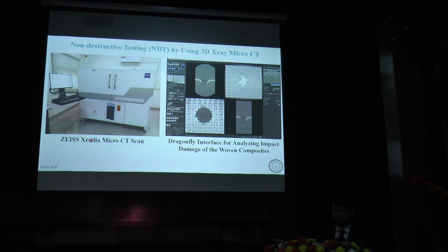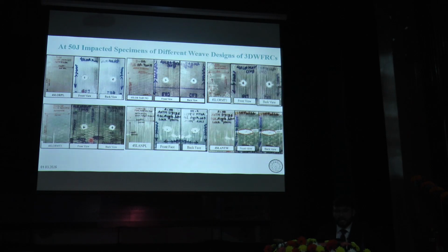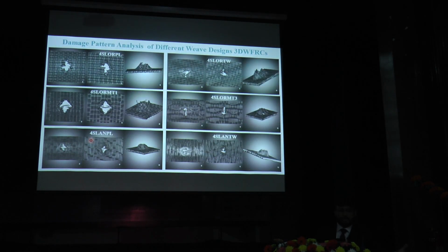And then we did the X-ray testing, and we tried to understand the perforation and the damage area of it. And it's telling me an incredible story. The structures with the basket form did not catastrophically propagate the crack. It stopped the crack in so many ways. You see, it's a very small crack. But for other structures, quite a big hole or puncture happened.